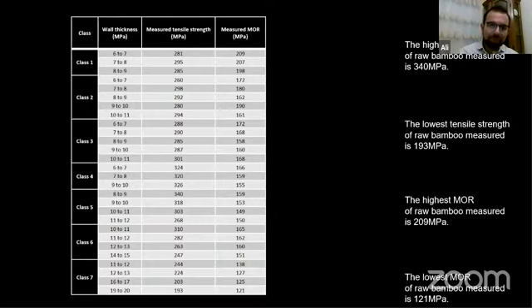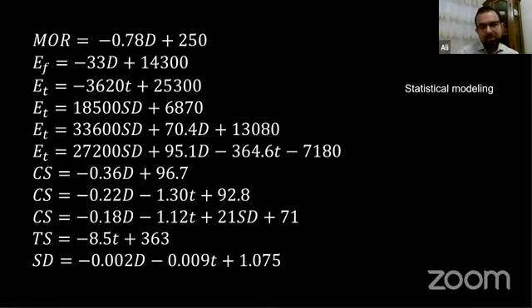But what was interesting for us was that the most common bamboo species in Southeast Asia was Dendrocalamus asper, and this is some of the classification that we did. We classified these bamboos according to their wall thickness, as well as their culm diameter. The maximum strength in terms of tension we found was 340 MPa, and the lowest was 193 MPa. As you can see, there is a wide range of mechanical properties between the bamboos that we collected. Even the same species grown in Southeast Asia, but in different regions, had different mechanical properties. And this shows another challenge where we wanted to promote bamboo, because the industry and even government agencies like the building and construction authority in Singapore see this as one of the main challenges: how we can standardize bamboo for use as a building material. But we did some statistical and mathematical modeling to see how we can estimate the mechanical properties without testing them.